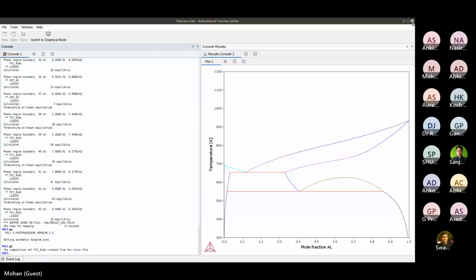But there is an alternate route to martensite transformation per se, where there are already existing good empirical models from Bhadeshia and others, where they relate the cooling rate, and there are nice estimations of martensitic start and end temperatures and the volume fraction that you will get at each temperature. Most of these models are athermal in nature, which means if you cool down to a particular temperature between MS and MF, you know the volume fraction that will come out. The temperature and therefore the volume fraction are well related, and experimentally there are already laws existing. Once you know the cooling rate that you can access in your process model, and you can also get it from the microstructure models that we are developing, you can then estimate the volume fraction of the martensite, which is already relevant information that can be derived from different parts of the measurement.